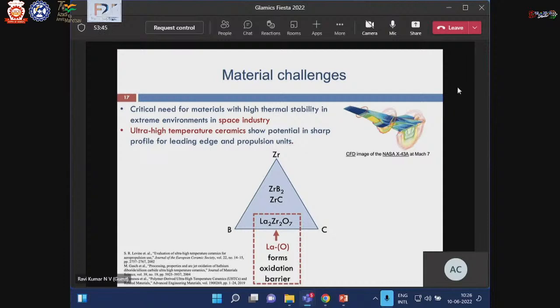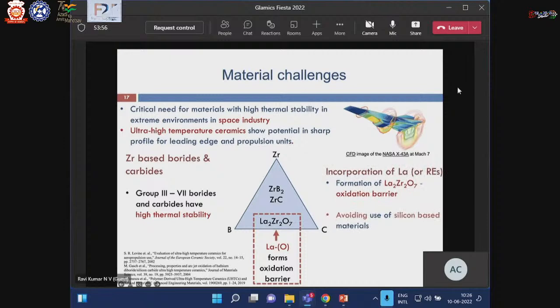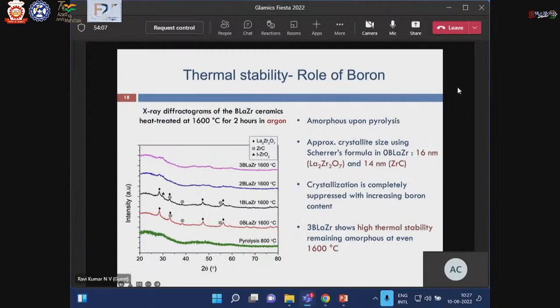Of course, we have some initial results based on lanthanum which I'm going to show you right now. We make sure that a phase such as lanthanum zirconate is formed, which is very useful because it acts as an oxidation barrier, while the other carbides and borides of zirconium provide high temperature resistance. Some of the preliminary results I'm showing here demonstrate that these materials are quite stable. You can see that even at 1600 degrees Celsius the material is still amorphous. Please note that our starting point is an organic precursor, which converts into an inorganic amorphous ceramic. Our idea is to make the amorphous structure as stable as possible at high temperature. So even at 1600 degrees Celsius, the material is predominantly X-ray amorphous.